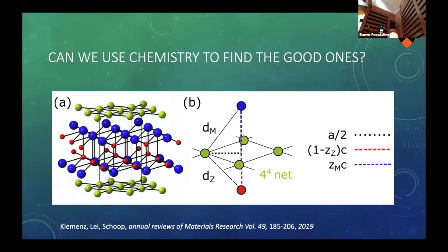And so what we did instead is we put up this hypothesis that if it's really a chemical bond which is responsible for these beautiful linear dispersed bands, then the atomic distance between these atoms in this densely packed square net needs to be shorter than the distance to the next atom above and below, because a chemical bond always reduces distances between atoms.